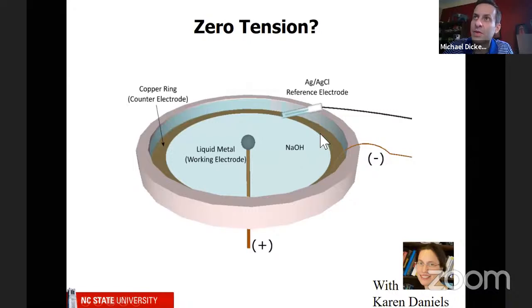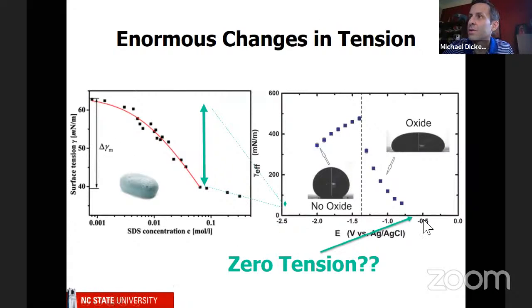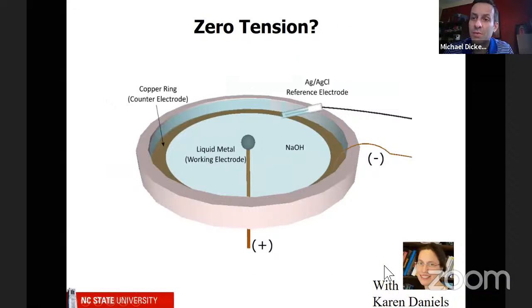So this is some work we've been doing with Karen Daniels in physics at NC State. And what we do is we put a droplet of liquid metal in a little dish, a little petri dish, and we have a counter electrode, which is this ring that goes around the outside, and we contact the liquid metal again with a little electrode underneath it. Now, in the video I'm going to play for you, I'm going to apply the voltage that looks like this should be 0 surface tension if you took this and projected it all the way down. And so we're going to look from the top down. And remember, if there's 0 surface tension, there's no energetic penalty for a material to spread. So let's see what happens.